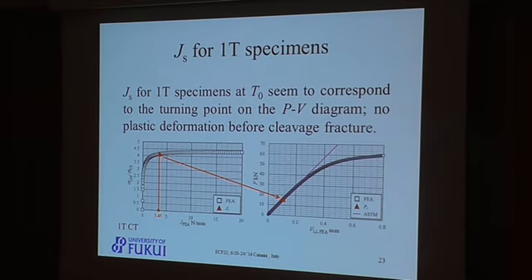Some rough side evidence we recognize is that the predicted JS seems to correspond to the turning point of the load versus load line displacement diagram. That is, if fracture is to occur at this load, then no plastic deformation is observed before cleavage fracture. Because we are considering elastic plastic fracture toughness JC, this finding seems to give some idea of the lower bound JC in a practical sense.